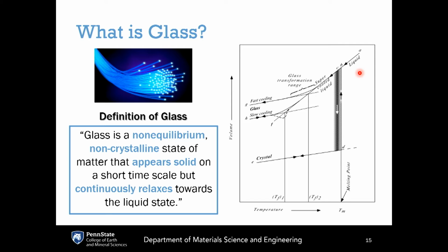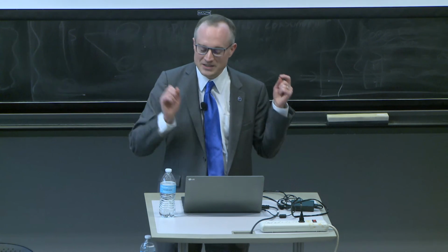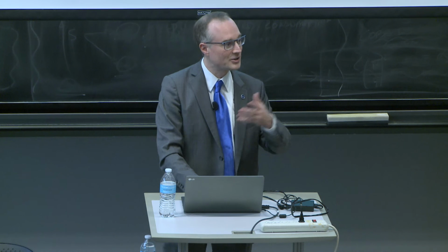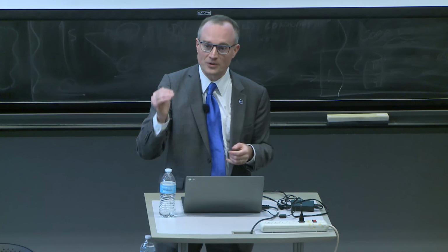So crystallization, is it something that happens instantaneously? No, it takes time. It takes time for the atoms in the disordered non-crystalline structure of the liquid to reorder themselves into a crystalline configuration. In some liquids, this happens very quickly, like water, for example. If you take liquid water and cool it below 0 degrees Celsius, it crystallizes quite readily because it's so fluid at that temperature.